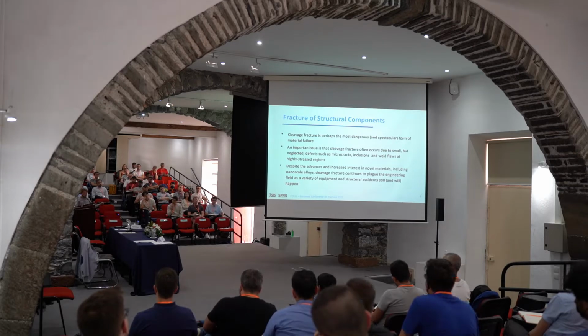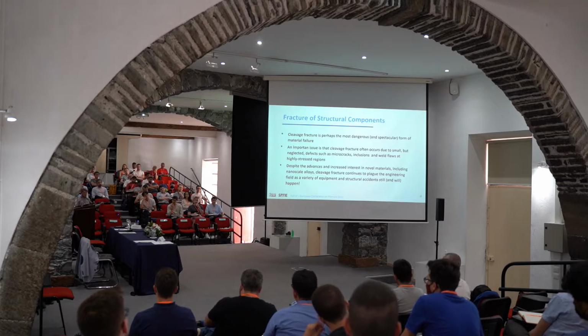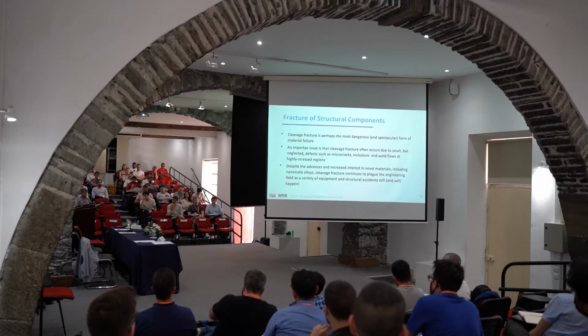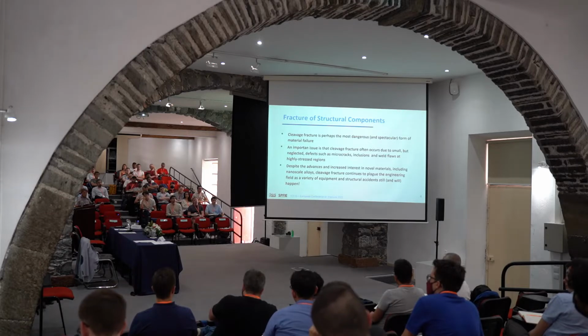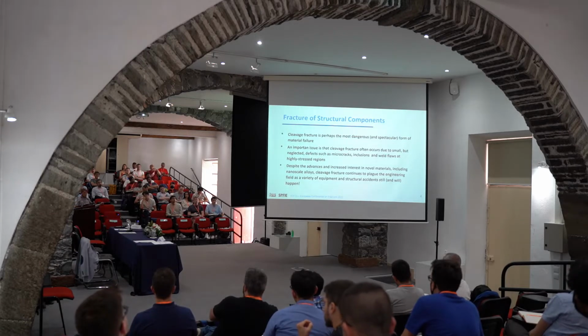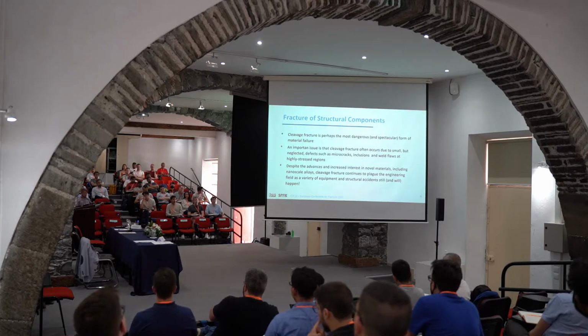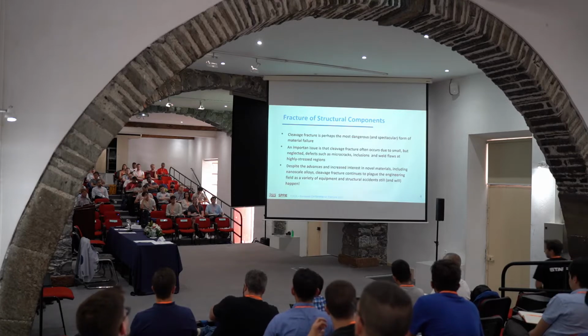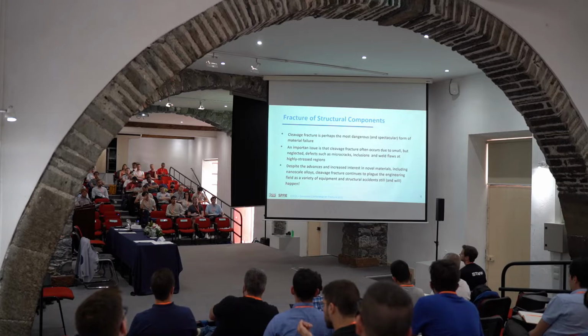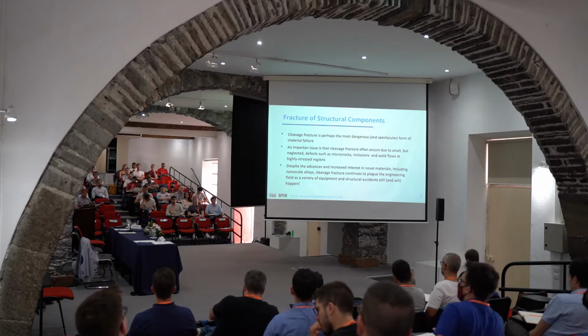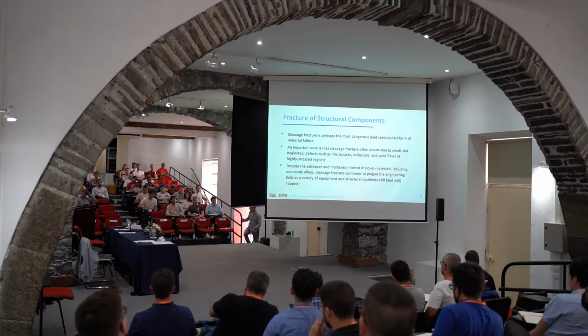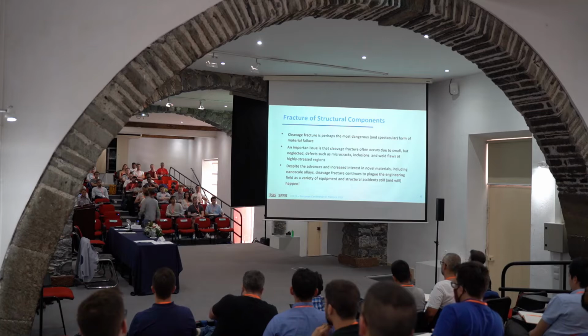So in general, most of these structures need to be welded, and the weldment is usually the weakest link of the structure, and also highly stressed regions. So, despite the advances and increased interest in, as I said, novel materials, including nanoscale alloys, which are a very strong trend for advanced applications, fusion reactors, high-end applications, for example, aerospace aircraft turbines, cleavage fracture is still a very important failure mode. So we see these happening almost every day, especially in the industry.